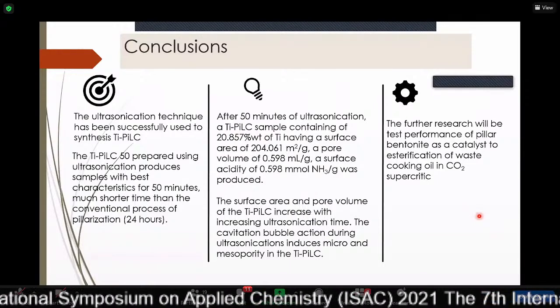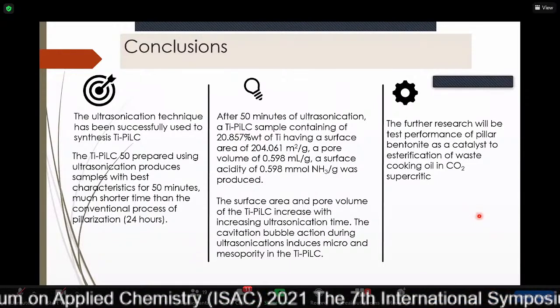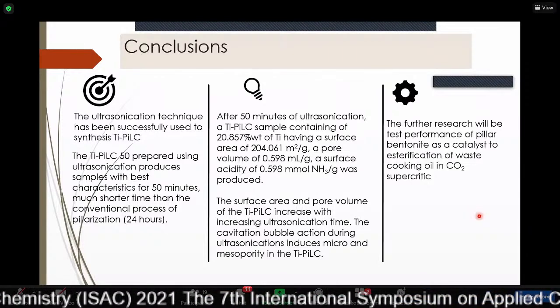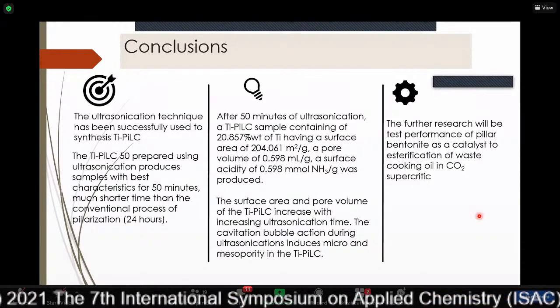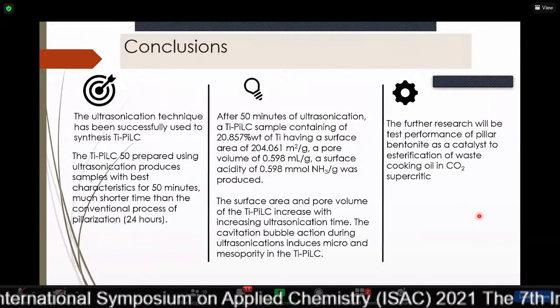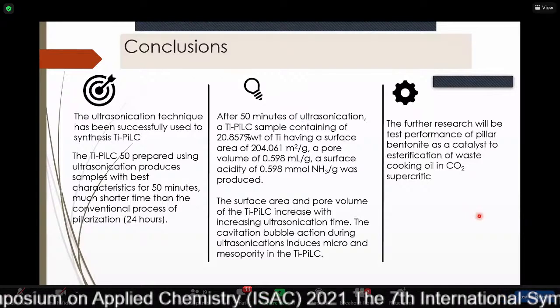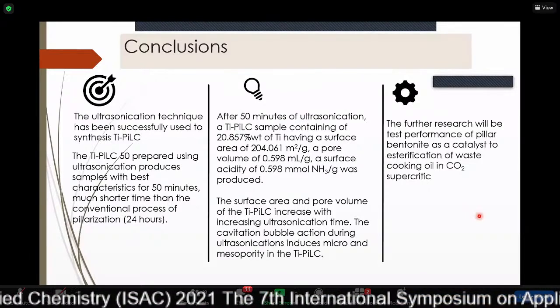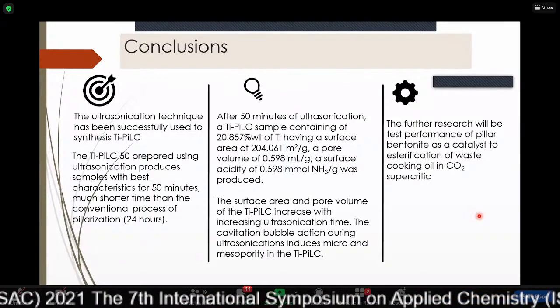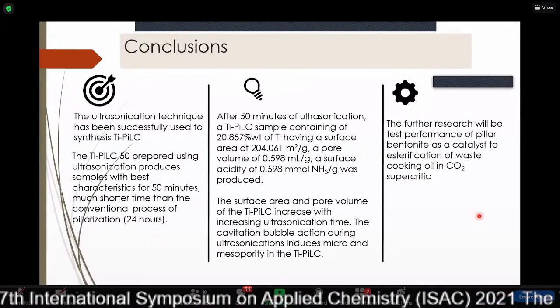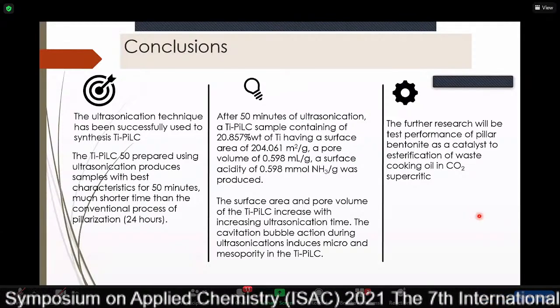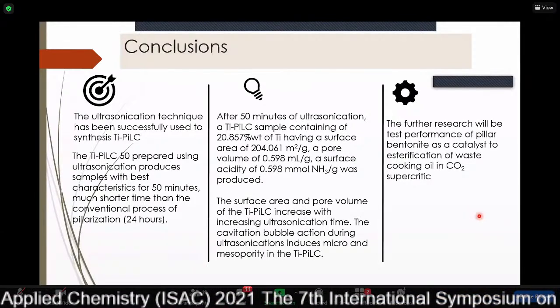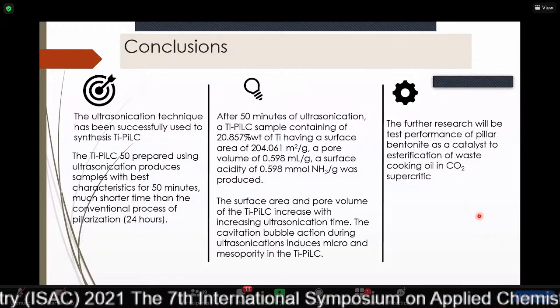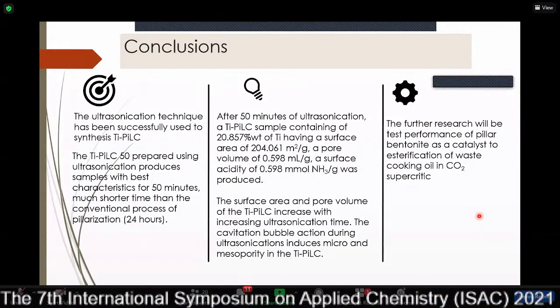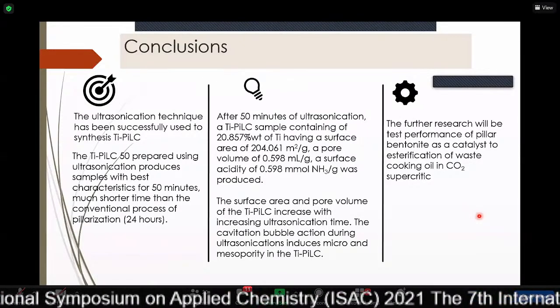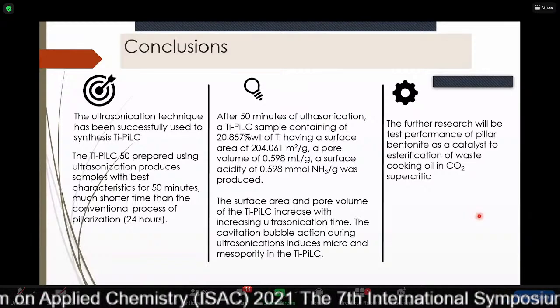The last conclusion: the ultrasonic technique has been successfully used to synthesize Ti-PiLC. Ti-PiLC 50 prepared by ultrasonic produced the sample with the best characterization in 50 minutes, a much shorter time than the conventional process of pillarization. After 50 minutes of ultrasonication, the Ti-PiLC sample contains 20.8 percent titanium, having a high surface area, high pore volume, and high surface acidity. The surface area and pore volume of the Ti-PiLC increase with increasing ultrasonication time. The cavitation bubble action during ultrasonication induces micro- and mesoporosity in the PLC and Ti-PiLC.